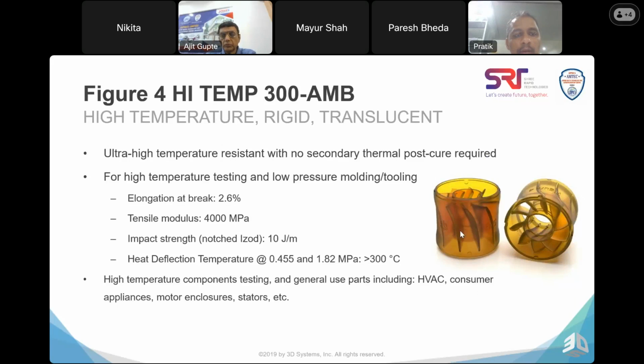This is one of the most unique materials of 3D Systems, which is the High Temp 300 Amber. It's basically an ultra high temperature resistant material with no secondary thermal post cure required. So it's used in applications which require high heat resistance. It can withstand temperatures of over 300 degrees and has a modulus of 4000 MPa. It is well suited for testing of high temperature components in applications including HVAC, consumer appliances, motor enclosures, stators, molds.